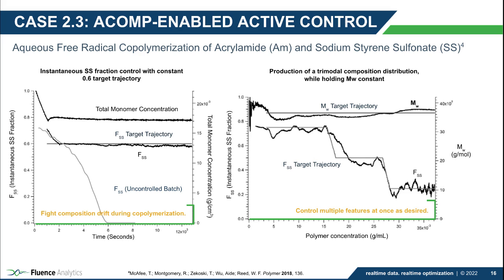Now going into composition control, a free radical copolymerization of again acrylamide and sodium styrene sulfonate was carried out. Now, the controller was successfully capable of keeping the sodium styrene sulfonate instantaneous fraction within the 0.6 target trajectory. And we can see how it compares to the strong compositional drift seen for the uncontrolled reaction.